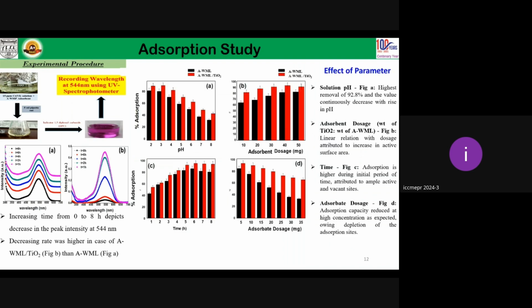Different parameters were studied. Figure A shows the effect of pH, B shows the effect of adsorbent dosage, C is the effect of time, and D is the effect of initial concentration. So it was concluded from here that our nanoadsorbent was giving a better result at a lower pH, and the optimized parameters at which the best result was obtained are pH of 3, adsorbent dosage around 40 mg, time around 60 minutes, and concentration of 5 ppm.